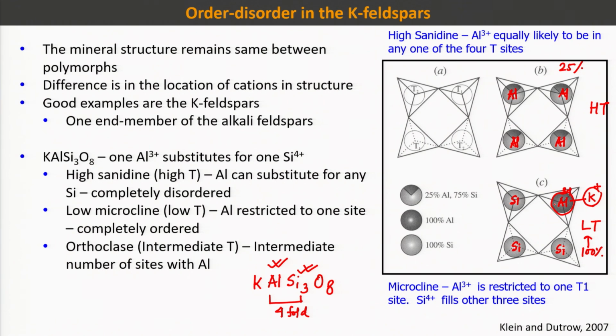So, this is the example of order disorder. Because at high temperature you form sanidine, which is a high temperature polymorph of K-feldspar. So, this aluminum can substitute for any silicon and it is a completely disordered structure, and microcline will form at a low temperature and this aluminum will go to one particular site. Okay. So, when you get sanidine in your rock, you should immediately understand that this rock is formed at a very high temperature, but if you find microcline, you should understand that your rock is formed at a relatively lower temperature. So, this concept is very helpful to understand the temperature condition of the system.